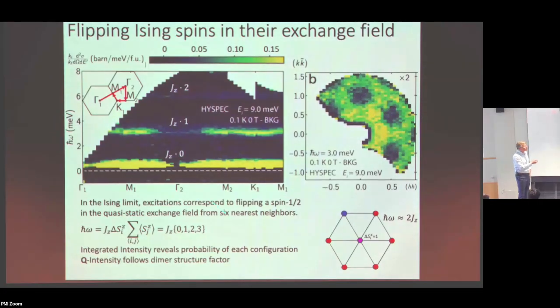Now, of course, this is an approximation because we do have the transverse term, and so the spin flip is not really just flipping a single spin. There are some correlations involved, and these go beyond the atom, because if I look at the intensity of this mode, you can see that there's some structure in reciprocal space. It lives along some boundaries. That means I'm not just flipping one spin, I'm doing some kind of rearrangement of the structure that reflects this wave vector dependence.